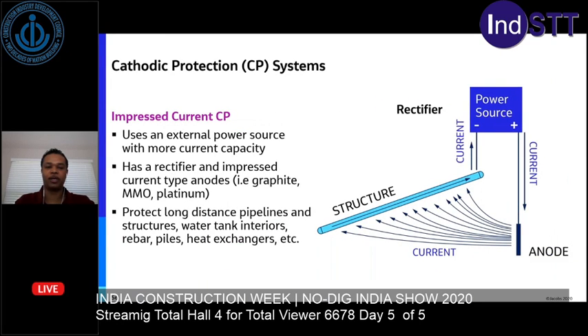You also can do an impressed current CP system. These are the systems that have the higher current capacity. It uses an external power source. You'll need a rectifier in this particular application. You'll need impressed current type of anodes. And these anode examples are graphite anodes, mixed metal oxide anodes, or platinum anodes. This type of system allows you to protect long distances of pipelines, water tank interiors, rebar structures, some piles, heat exchangers, and there's a multitude of areas that you can protect with this impressed current system. Next slide.